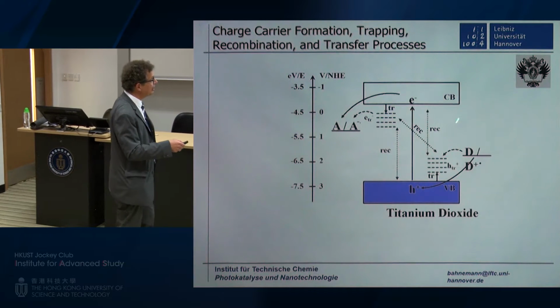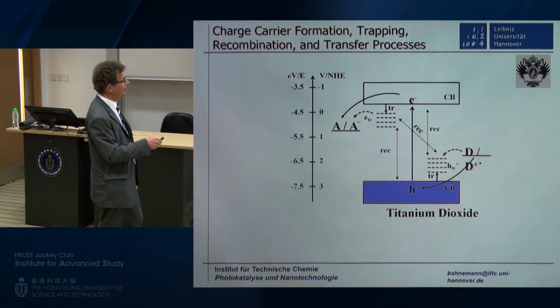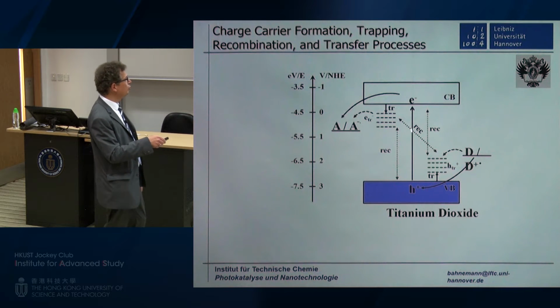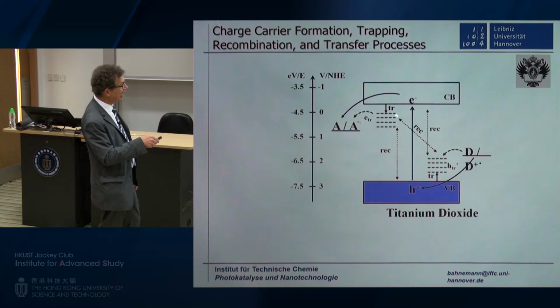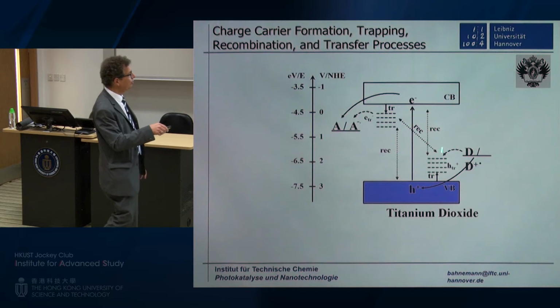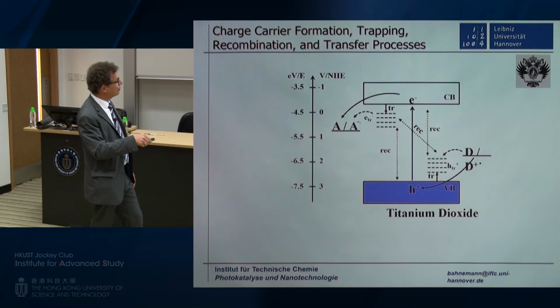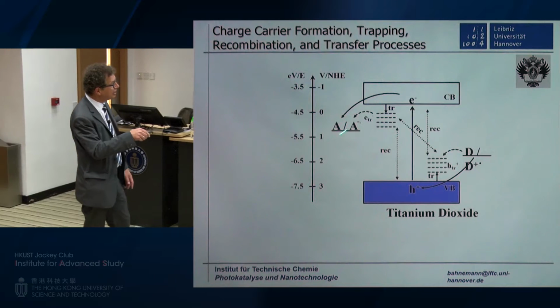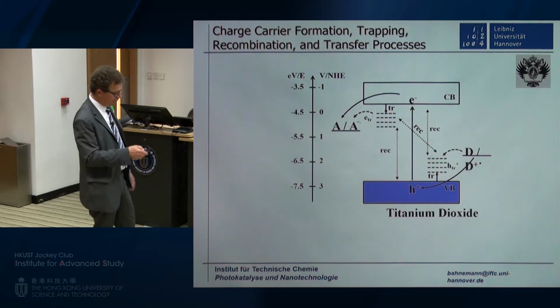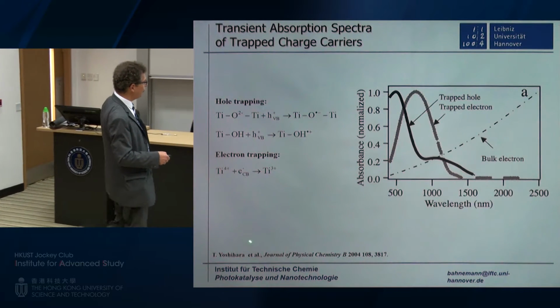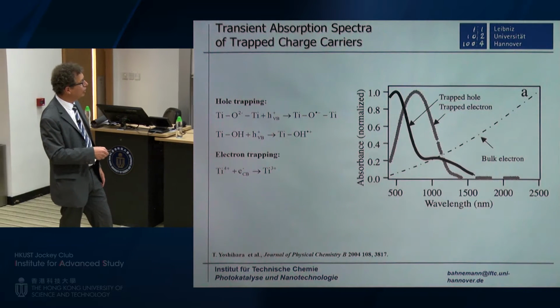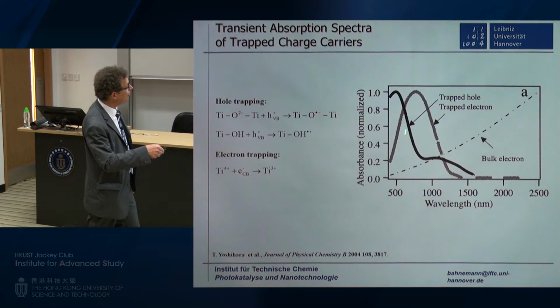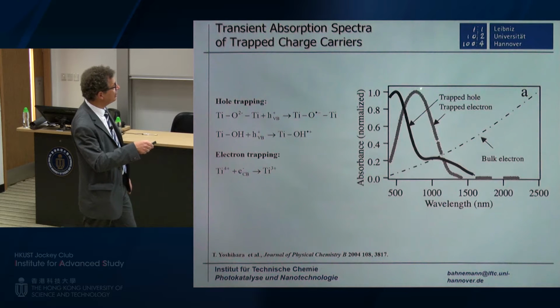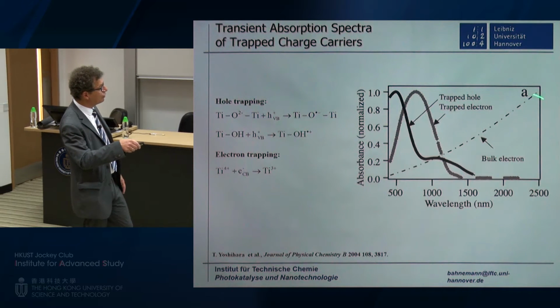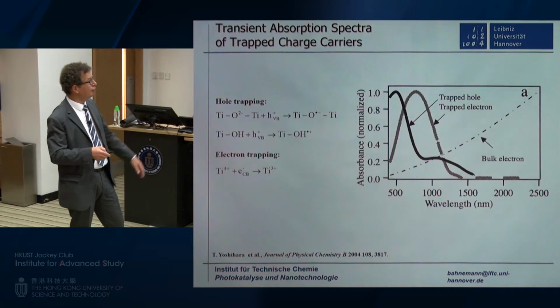And we know that the mechanism is at least as complicated as this, that the electrons and holes you form, they will go into traps, and these traps can act as recombination centers. They can also recombine with untrapped charges, and so on, and you can also have direct recombination. So this is a reaction you want to bring about, but all this is a very complex system. There have been nice review papers, for example, by Yoshihara and co-workers, showing that besides the trapped electron that we had discovered in 1984, the trapped hole actually has a second band in the near infrared, and the bulk electron can also be observed in the infrared, so you can observe all these beasts.